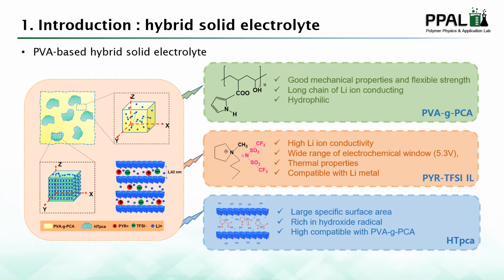So here, we set the concept of the association of strong attraction and mechanical strength of the PVA and the wide electrochemical window and excellent thermal stability of pyrrolidinium-based ionic liquids, and their combination can express the superior characteristics of a solid polymer electrolyte and wider application. However, as the synergetic effect of the PVA and the pyrrolidinium-based ionic liquids blend is mitigated by the immiscibility between them, their compatibility is purposely improved by grafting the PVA with the PCA unit, and the 3D matrix of the well-constructed PVA-grafted PCA and ionic system not only enables feasible interaction with the lithium ion by the abundant and electronegative groups, but also provides effective lithium transport in the presence of the ionic liquid.